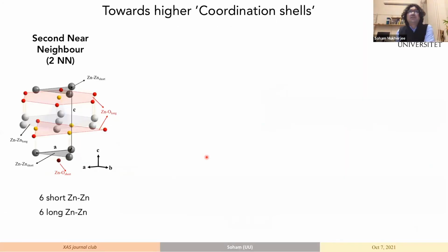So with this, we'll start looking at the second near neighbor. I have drawn the hexagonal system, and you can see that there are six short zinc-zinc distances and six long zinc-zinc distances. These are marked with this particular gray colored atom. The dark gray ones are the shorter distance, and the ones in this plane, there are six zinc around the zinc, so those are my longer zinc-zinc distances. Of course, now this is a doped sublattice, so this has a mixture of zinc and cadmium.